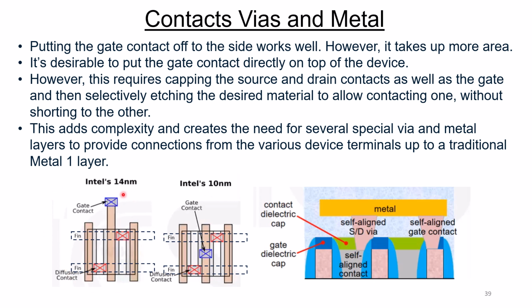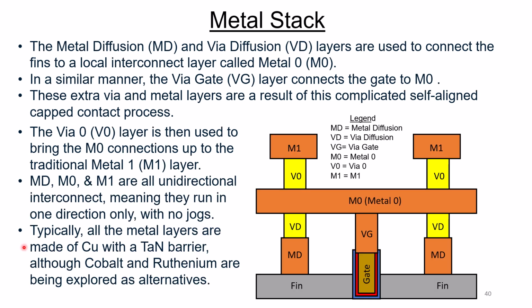So if we look down here, this shows the gate contact off to the side. And this was pretty convenient. However, again, like we said above, it takes up area. So you'd really like to put that contact right smack on top of the gate region. But in order to do that, you have to do this special capping process. So not only are we capping the gates now, we're going to be capping the source drain regions and then selectively etching through these caps to allow self-aligned contacts and vias without shorting out to the adjacent gate or drain source contacts.